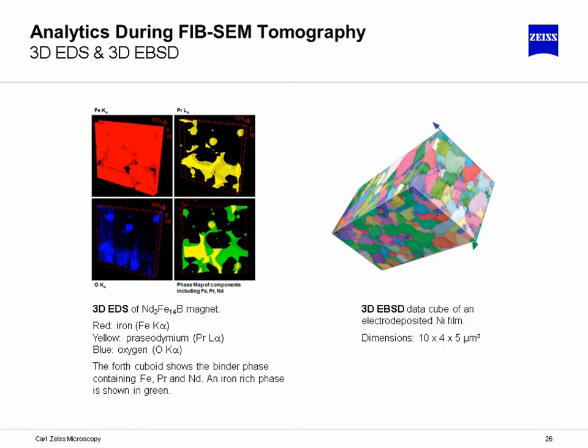To finalize this section on FIB-SEM tomography, just a short note on 3D analytics. Both the acquisition of 3D EDS and EBSD datasets is possible. On the left, you see an example for a 3D EDS dataset on a magnetic material. In red, you can see iron, in yellow and blue, praseodymium and oxygen. The right image shows an example of a 3D EBSD dataset. The sample is electrodeposited nanocrystalline nickel.